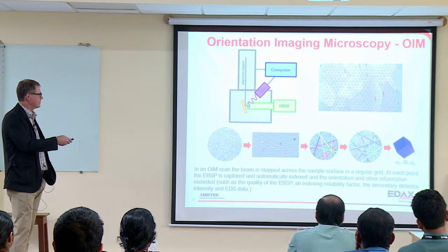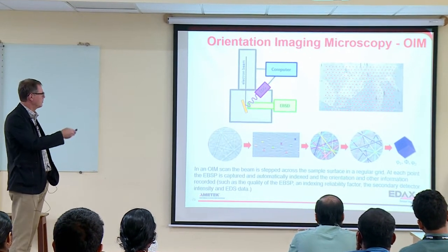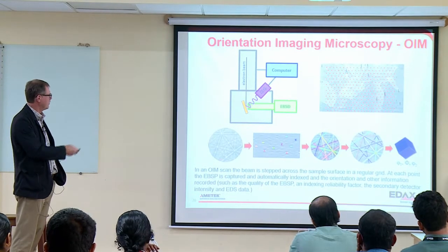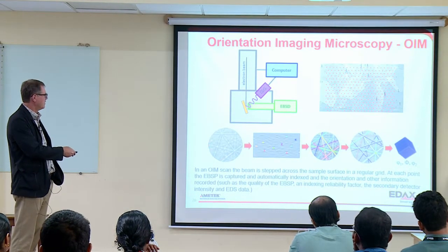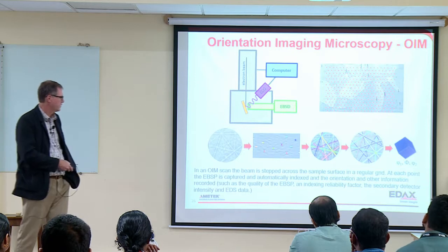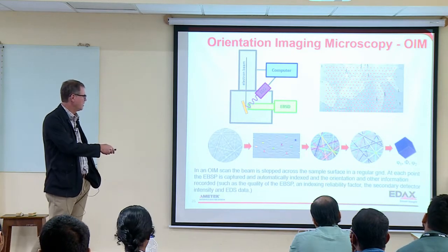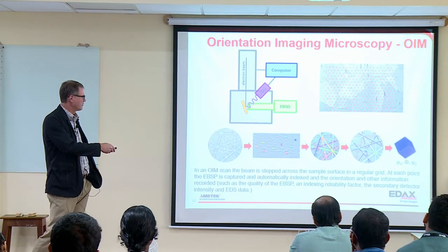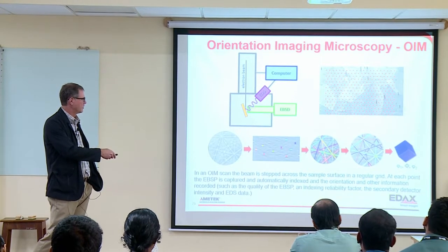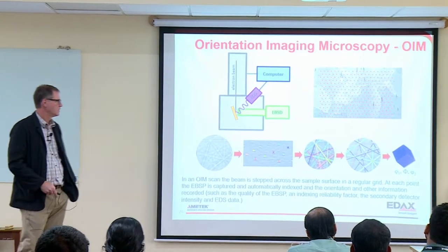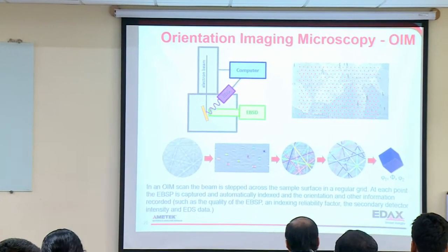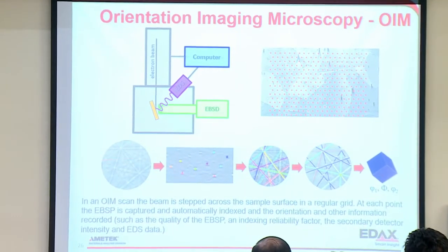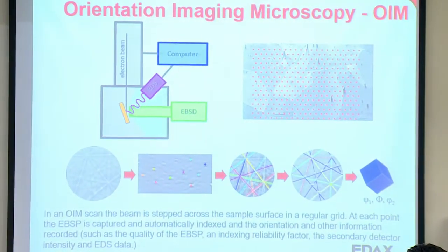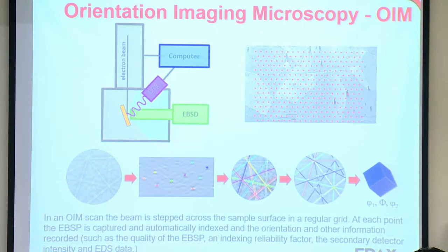So now we've added this into the mix, the EBSD detector. What we have is the electron beam. We move it to a point. We capture a pattern. From that, we use something called the Hough transform to find the bands in the pattern. Once we find the bands, we look at the angles from them, and we're able then to determine the crystallographic orientation, and we record it to the disk in terms of 3 Euler angles in this example. And I'll go through these steps, but we call this whole process indexing. This is indexing an EBSD pattern.